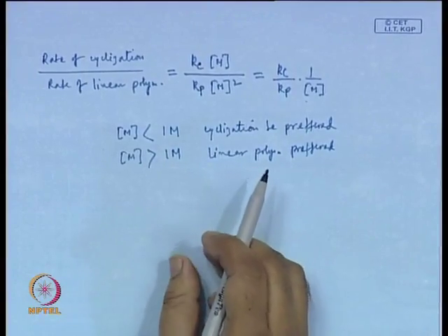So, it is always advisable that to minimize cyclization, we use the maximum possible concentration of the monomers, and the best we can do is a bulk polymerization, that means we carry out the reaction with just the monomers and the catalyst if required. That is the maximum possible concentration you can have to minimize cyclization.